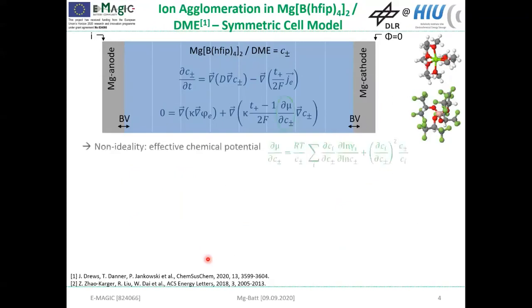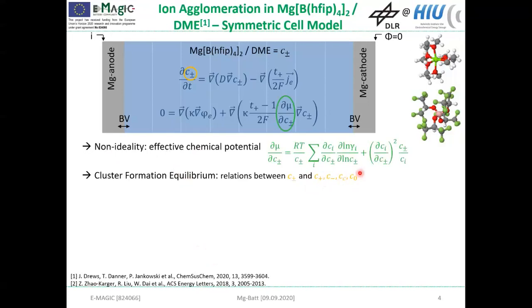So as I told you, the non-ideality effects may play an important role in magnesium electrolytes, and therefore we consistently included the non-ideality via the effective chemical potential. And then the cluster formation equilibrium, which I showed you in the last slide, gives us a relation between the electrolyte concentration and the concentration of the dissociated ions, the cluster, and the amount of free solvent.